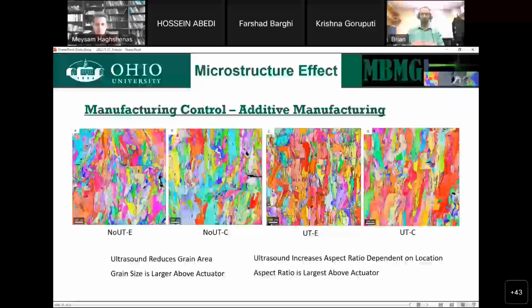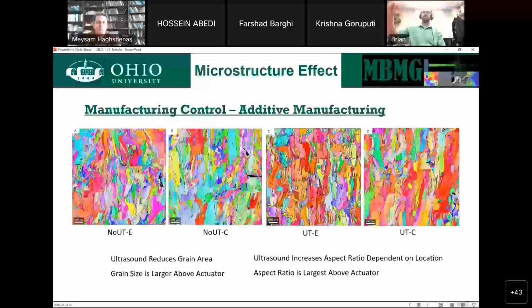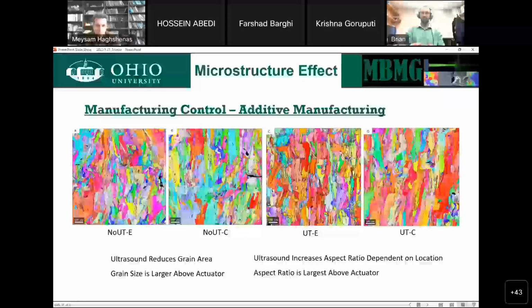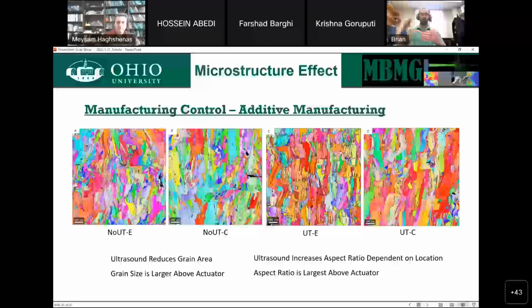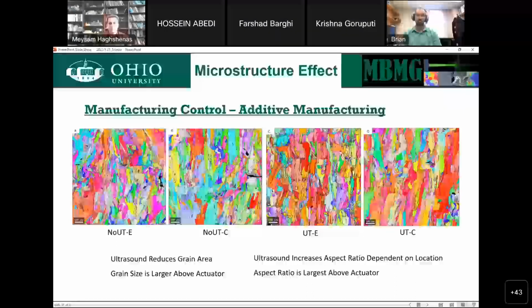So it really ties into the intensity as to whether or not you see size change on the grain. The lower the intensity, the more subgrain you change. As you increase intensity, you start to affect the actual grain size itself. And there's a balancing of energy from the laser that has to happen for this too.